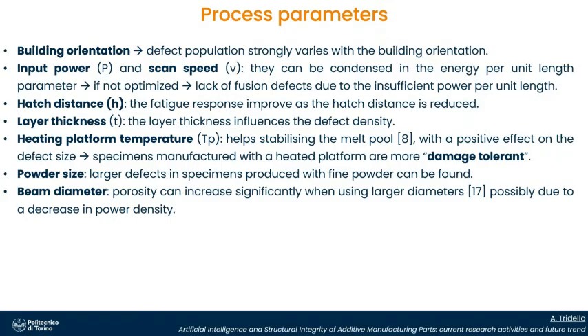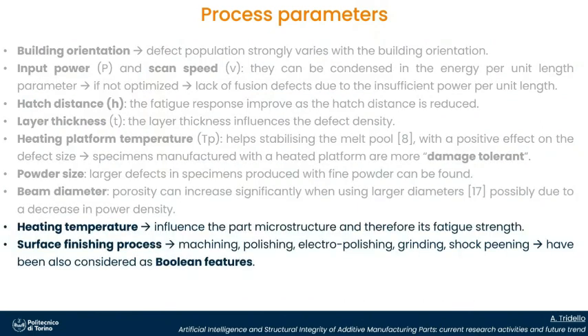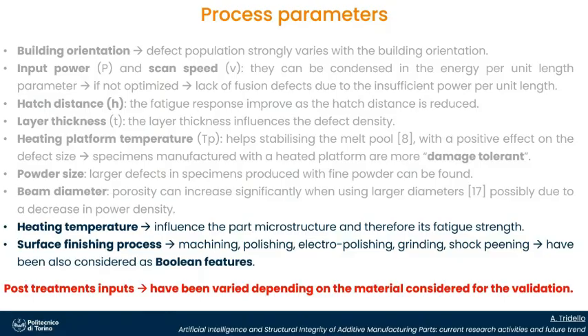We rely on literature data, so we consider this one, the most important one, and the ranges are those available in the literature. We consider also the heating temperature to take into account the heat treatment and also surface finishing processes, this one. And we consider them as Boolean features. So if the process is present, we set the Boolean feature to true, otherwise we set it to false. Okay. The post-treatment input can be varied depending on the material considered for the validation, since we have validated different algorithms, different materials, and we have to trust the data that we have found and that are available in the literature.